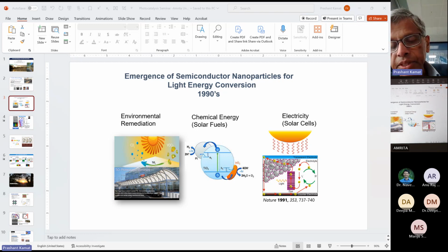So, for example, you can make cadmium selenide. But surprisingly, if you make cesium lead bromide with the normal oleylamine and oleic acid, we have tried it, you cannot electrodeposit. But when we had this CdS shell, we were able to deposit because the zeta potential became negative. So that was just for testing purposes. We didn't use it for this one, but there is another paper we published earlier where we made lead sulfate capped cesium lead bromide, and we could deposit it on the electrode, and we even made LEDs from those kinds of films.